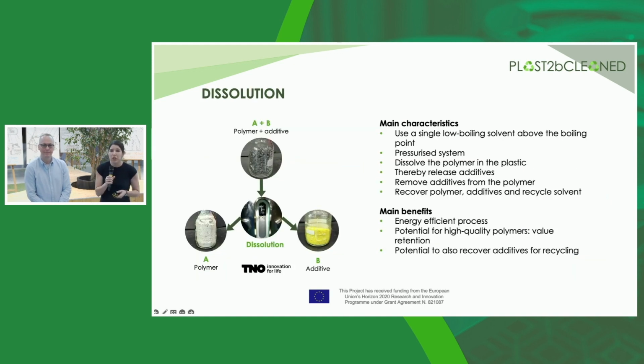Just a brief introduction into the dissolution process. So at the beginning we have a polymer with certain additives that are added to provide variable properties to the plastic. In the dissolution process, together with a solvent, the process allows for the separation of polymer and additive. In a Plast2bCleaned process, we rely on a single low boiling solvent that is used above its atmospheric boiling point. It's then a pressurized system, and it allows for the dissolution of the targeted polymer in the plastic. We can then remove, separate the additives, and at the end we recover polymer additives, and we can also recycle the solvent.